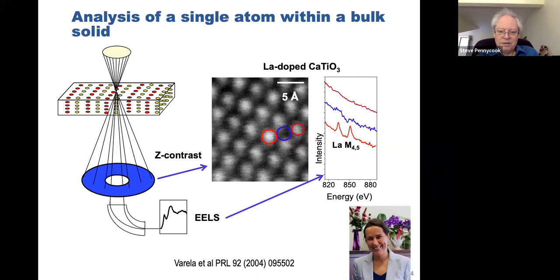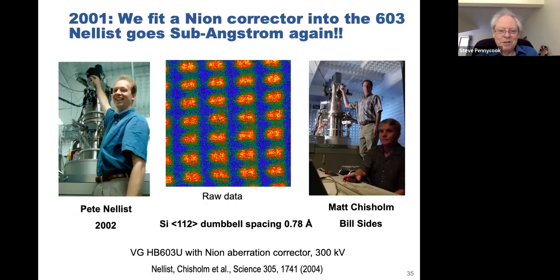Maria Varela was there also at the time. She used the machine to find single atoms of lanthanum. And you could see them in the image and you could identify them in the EELS, even with atomic resolution. Pete Nellist came back from time to time. He came back when we had an aberration corrector, again, thanks to Andrei, on the VG HB603. And actually, you'll notice here, Pete can reach this top aperture by standing on the floor, whereas this is Bill, the technician, and most of us had to stand on a step stool.